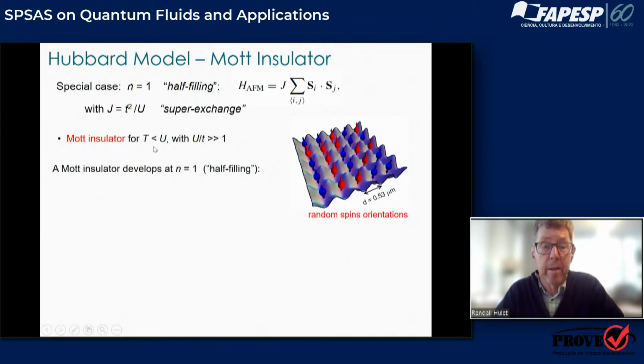So it turns out that if temperature is less than U and tunneling is much less than U, then a Mott insulator develops where there's exactly one atom per site, and that's called half filling, and this is kind of what it would look like. You have a bunch of downspin atoms in blue sprinkled over the lattice with the same number of upspin atoms that are shown in red. And they're kind of randomly distributed throughout this lattice with no magnetic order.